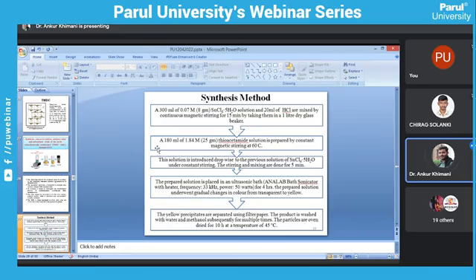Then a 180 ml of 1.84 molar, 25 gram thioacetamide solution is prepared by constant magnetic stirring at 60 degrees Celsius. Then this solution is introduced dropwise to the previous solution of SnCl4·5H2O under constant stirring. The stirring and mixing are done for 5 minutes.